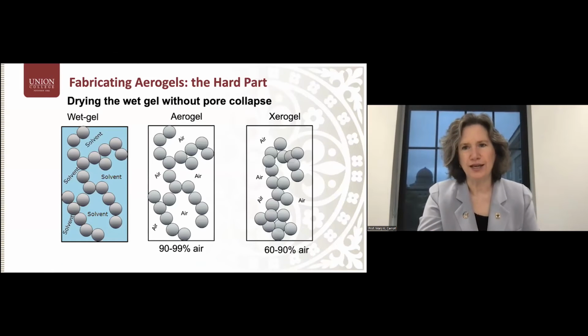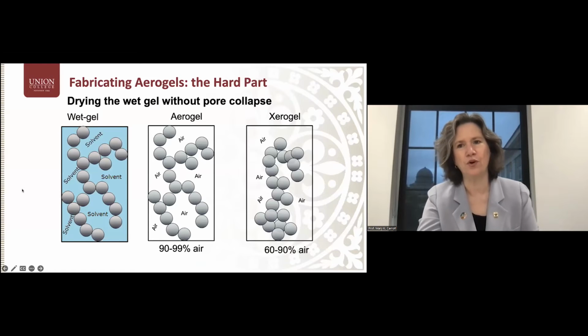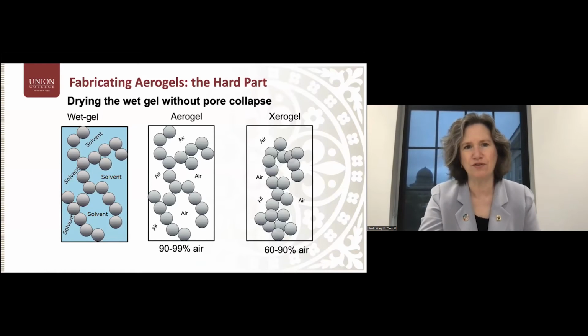The difficult thing about making aerogels is not making the network, the solid network. There's a lot of established chemistry for that. The difficult part is drying that gel without the pores collapsing so that the pore structure remains intact.